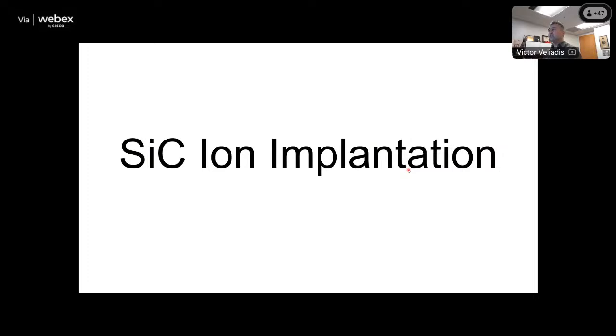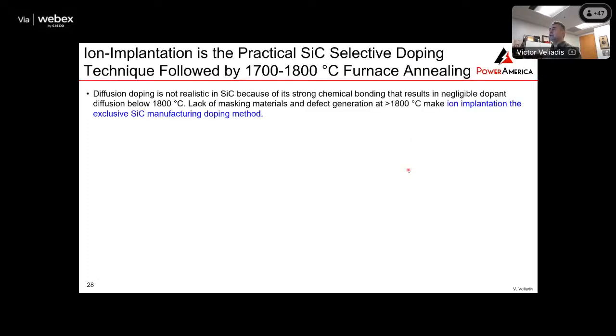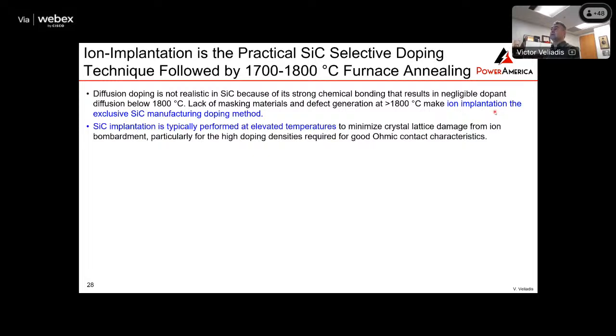Okay, ion implantation, that's another area where silicon carbide differs from silicon, and you need to develop specific processes. As I mentioned at the beginning, diffusion, which is a temperature effect to spread the dopant atoms, does not work in silicon carbide. So therefore, we're using ion implantation. It's performed at high temperatures.